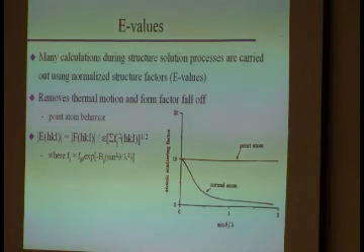So what an E value is basically the F value divided by the sum of all small fj squared, where this one contains both the F that comes from the atom and this term from thermal motion. So the advantage is that your data often looks a little bit cleaner when you do that one, and that's why people prefer working with E values, not with F values.